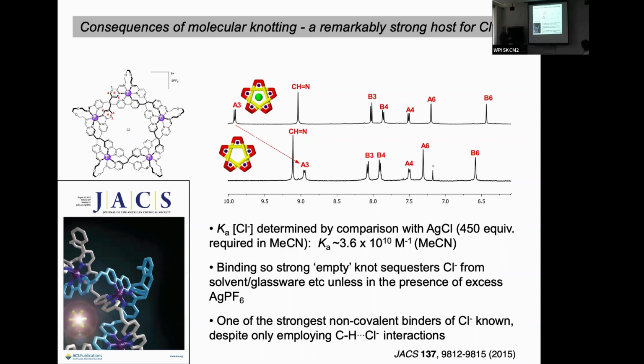And in fact, these knots are some of the strongest binders of chloride that are known. They have a binding constant of about 10 to the 10 in acetonitrile.